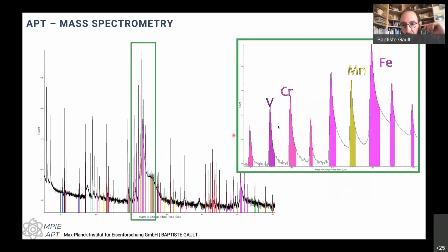So if I get back to, why is this not working here? Here I can see all the peaks really nicely separated, because after the laser pulse has heated the sample, it can cool down quickly. So the drop here in the peak corresponds to how fast I can quench the surface. But for some of these glasses that don't conduct heat so well, instead of having nicely defined peaks like this, you might have a long tail that will overlap with the next one and the next one. So it really comes down to what you might be interested in looking at in some of those samples.